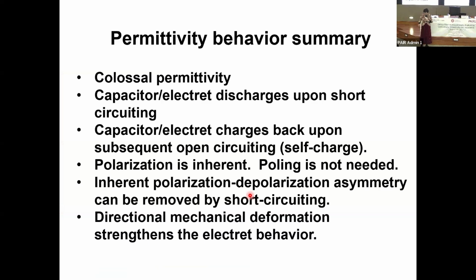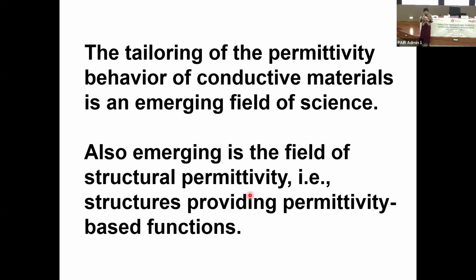The capacitor electret discharges upon short circuiting and charges back upon subsequent open circuiting, and this is self-charging. And the polarization is inherent. Poling is not needed. The inherent polarization-depolarization asymmetry can be removed by short circuiting. And the directional mechanical deformation strengthens the electret behavior. The tailoring of the permittivity behavior of conductive materials is an emerging field of science. Also emerging is the field of structural permittivity, that is, structures providing permittivity-based functions.